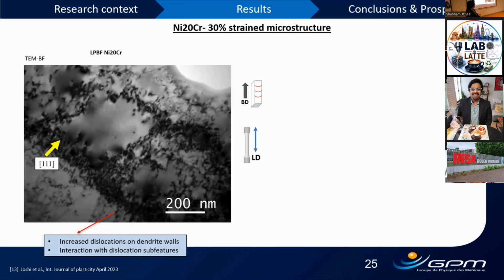So this is a 30% strained LPBF sample. The building direction is upwards and the loading direction is given. Again, sorry for the basic illustrations. What we see here is again somewhat the stability of the dislocation cell structures or the dendritic structures, whatever you want to call them. And qualitatively, it looks like the walls have thickened. That means the dislocations have interacted.